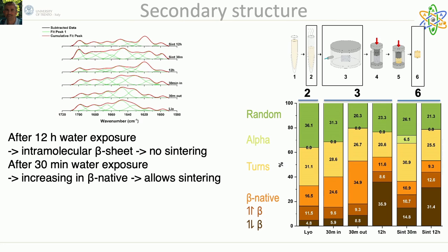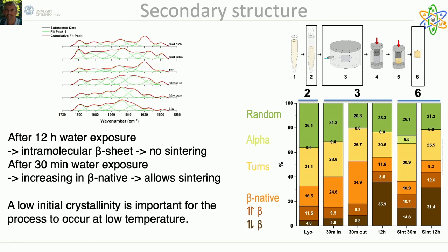When exposed for 12 hours instead, beta sheet content rose to almost 36%, and the overall stable beta contributions, parallel and antiparallel, to almost 45%. After sintering, the sample exposed for 30 minutes to water could maintain the contribution of stable beta sheet low, while samples sintered after 12 hours of moistening didn't change significantly the overall crystalline structure and resulted completely not sintered.